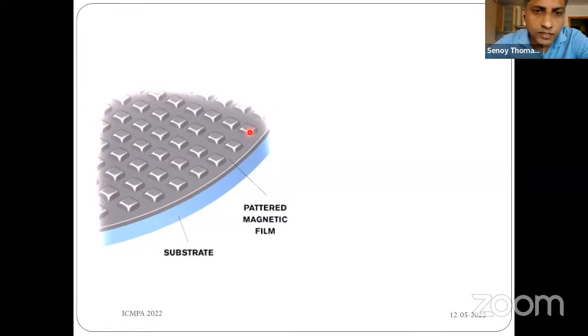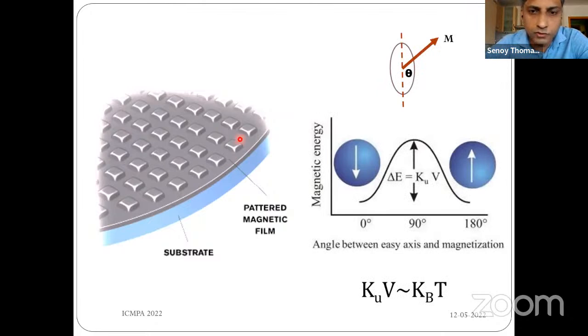Typically, these islands are made from magnetic materials having uniaxial anisotropy. For such materials, if the magnetization direction has to be reversed from one particular direction, let's say from the bottom orientation to the top orientation, then the system has to overcome an energy barrier. This energy barrier is the product of the uniaxial anisotropy constant Ku and the volume V of the material. So it also means that one cannot simply reduce the volume of the magnetic island so as to increase the areal density of the hard disk drive.